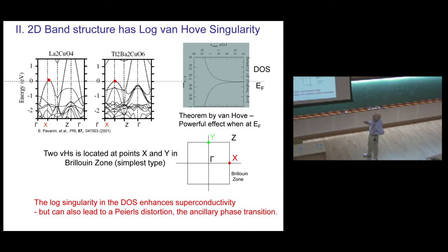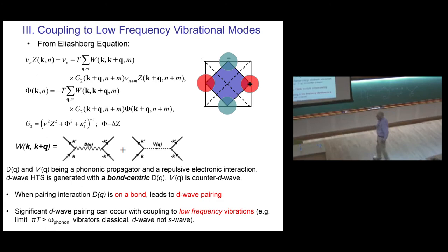Now we come to the band structure. This is the band structure of two of these materials. I want to point out these two red spots, which are actually saddle points. The band structure goes down here and up in the transverse direction. When you have a saddle point in a two-dimensional band structure, Van Hove showed in the 30s, you get a log singularity in the density of states. In the Brillouin zone, it looks like this. There are two Van Hoves, at Y and at X. That will turn out to be extremely important.